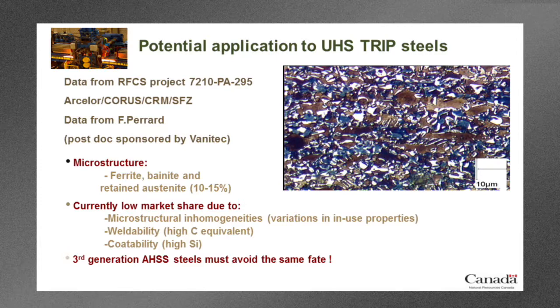Now you can see the microstructure on this image here on the right-hand side of the screen. It's a very complicated steel microstructure. There are three phases present: ferrite, bainite, and residual austenite. The residual austenite phase is in white in that diagram. TRIP steels, transformation-induced plasticity steels, are very complicated in terms of their microstructure and their mechanical behavior, but they do have some excellent properties.